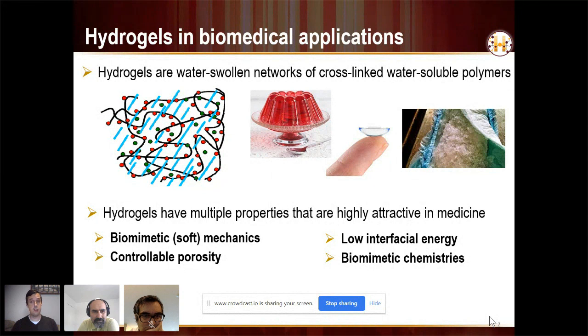We can control the interfacial energy and maintain it low because of the high water content of the gel. So when this gel is placed in an aqueous environment, there's very little difference between the free energy of the interface, which is already mostly water, and the bulk solvent. And if we want, we can make these with biomimetic chemistries, where the chemistry of the gel matches or is very close to those chemistries we find in native tissues.